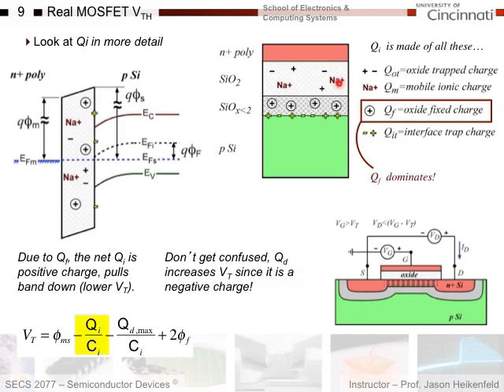The other charges you'll see in here are these oxide trap charges. These are mainly just for defects and other things, but their net charge tends to cancel out, so you don't have to worry about those. You have an interface charge down here, which can be plus, minus, plus, minus. It kind of cancels out, but it's going to come back later. We're going to see that this causes some problems for us later, but it doesn't really dominate this threshold voltage shift. What does dominate is this oxide fixed charge.